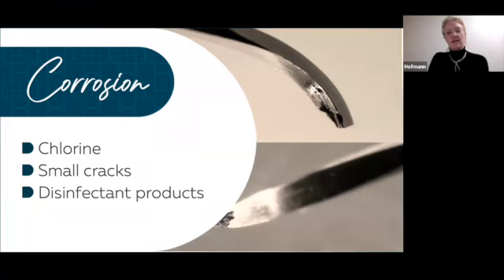The corrosion is something you will not see immediately, unless you look at them very often with the loupe, because corrosion can occur through little cracks, and the first thing you will see are little black stains on the tip of the instrument, for example, and the corrosion will occur inside the instrument, and suddenly the tip will fall without any force, of course.